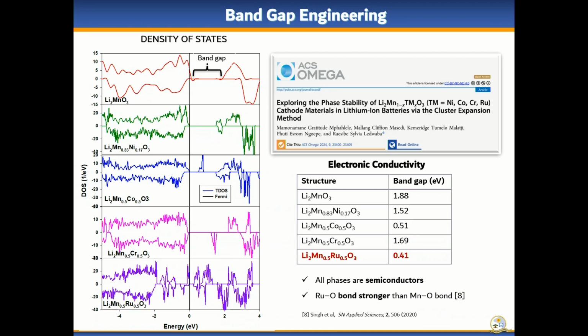Another one on elemental doping was an MSc study done by Mamunamani Mphahlele, who's also in the room. During the study, she used cluster expansion, where she was able to come up with new stable phases. And from the most stable phases, we were able to identify that the band gap was actually modified from the original band gap of the semiconducting material. We're able to reduce the band gap, and the lithium manganese ruthenium oxide system actually has the lowest band gap, and this means that it conducts better than the parent structure. And when we looked into literature, we found that the ruthenium and oxygen actually bond much stronger than the manganese and oxygen. And this gave us even better explanation onto what is happening.